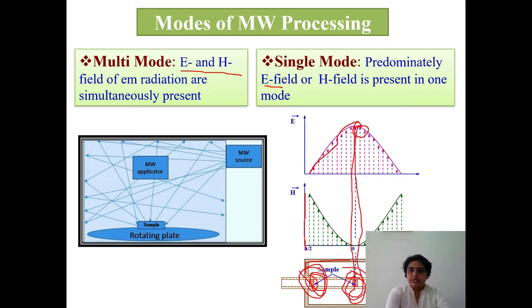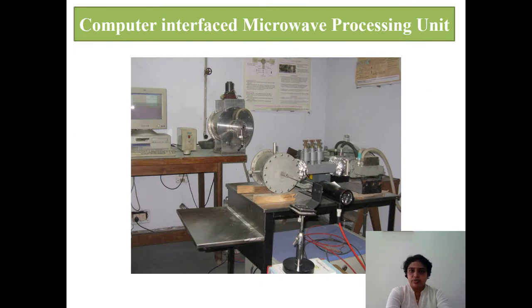So let's go further. This is the system which I used during my PhD work. This is a multi-mode applicator, where both modes were present, and this is a single mode applicator. With the help of the waveguide, calculator and everything, only one mode was present at the center. This is the H field. At the center of this cavity only the H field was maximum, and we kept our sample in a quartz tube, which goes inside the applicator, and we can heat our sample in the H field. Then there was one more assembly, a similar kind of applicator designed for maximum E field. Generally we use that E field applicator for dielectric material and this H field applicator for magnetic material.